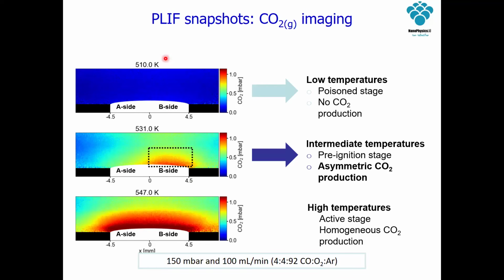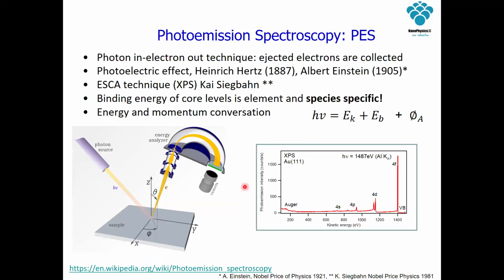So basically, if we have a low temperature, nothing happens. And then from a certain temperature on, in this case around 530 K, we see that we illuminate this side. So here we are now producing CO2. And then a little bit later, around 5 degrees later, the A side gets active, and finally also this 111 in the middle. So we have some asymmetric CO2 production. We have some pre-ignition that happens first on this B side. So we now know that a stepped surface with B-type steps is much nicer than a flat crystal, but we do not know what happens.